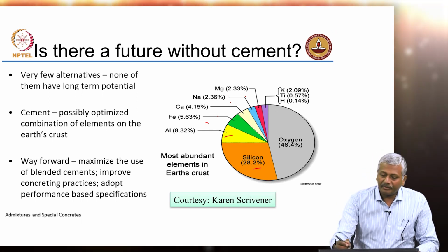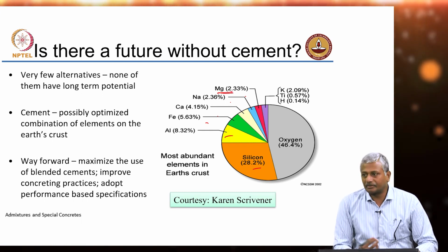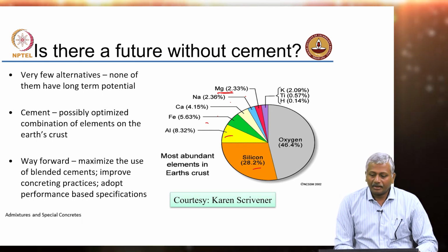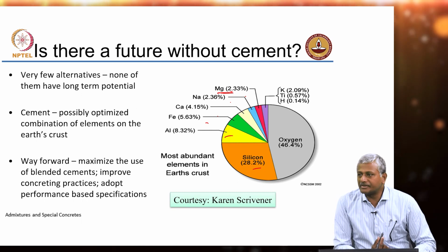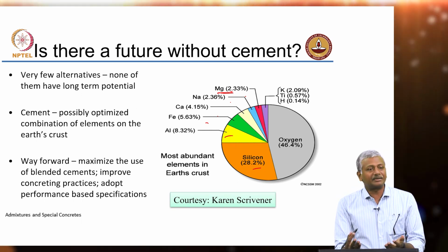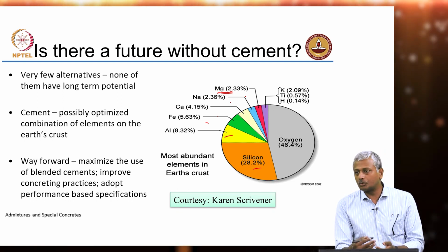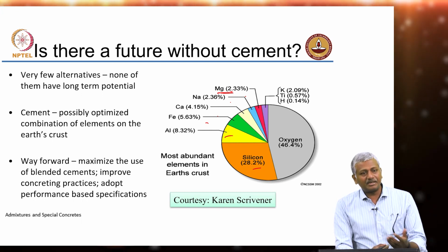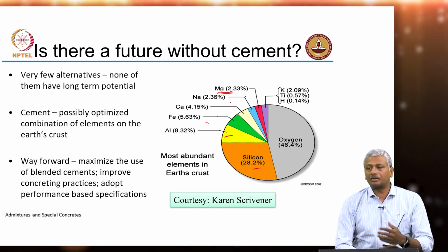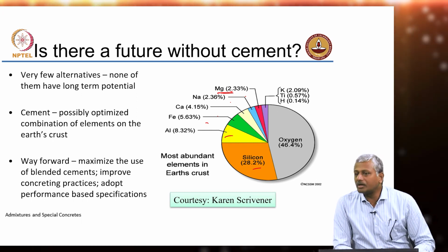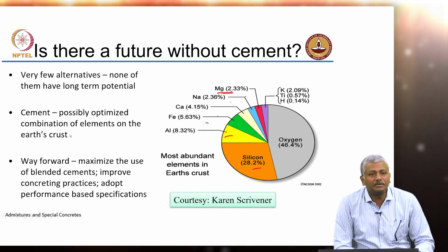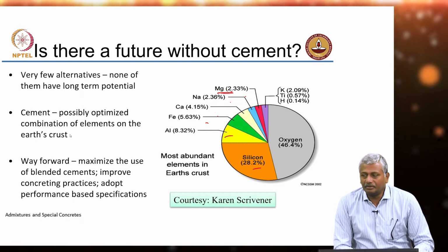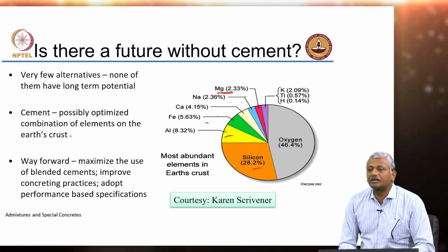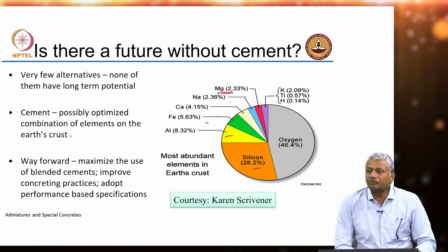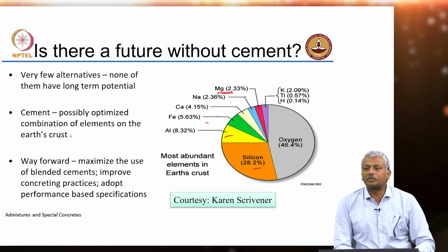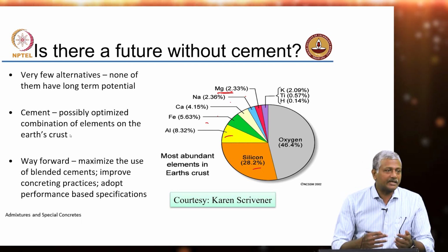crust. You also have other cements which we will not talk about during this course, but there are some special cements that are based on magnesium, magnesium phosphate cement, magnesium oxychloride cements and so on. Problem with those is then you really can't manufacture those at any bulk level like you do for Portland cement. So, it is not easily foreseeable that an alternative cementitious material could replace Portland cement for the kind of quantities that we use. How much cement do we use every year? About 4 billion tons, more than 4 billion tons. So, we are talking about 4 gigatons of cement being used every year, and for that kind of quantity you do not really have the raw material necessary to produce alternative cements as much in abundance.